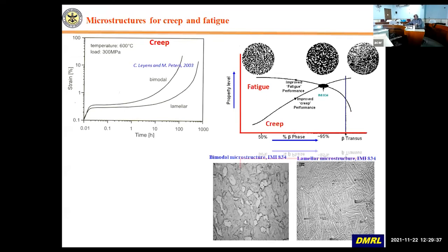Now, here there are two microstructures, bimodal and lamellar, where creep strain has been plotted. So here I'm showing you the bimodal microstructure has got worse creep as compared to lamellar structure. So lamellar structure is good for creep.